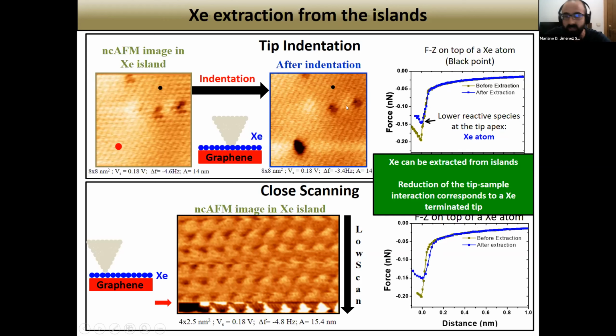So, summarizing this slide, the idea is that xenon can be extracted from the island, and that after this extraction, we observe a reduction in the tip-sample interaction that corresponds to a xenon terminated tip.